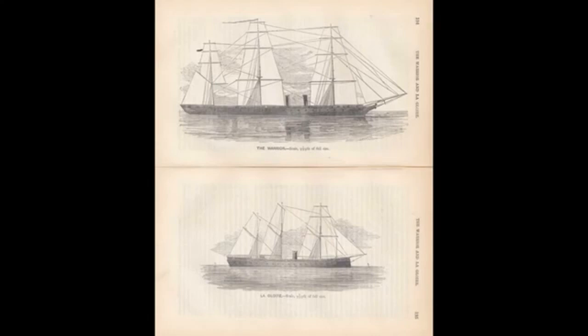Warrior's iron hull was a much better platform to mount the armour to, but its own plates were fitted together with tongue and groove joints. The theory being to distribute impacts that occurred close to the edges of a plate to adjacent plates, which was a good idea in principle, but turned out to be substantially less effective in practice, and the tongue and groove fitting made replacement and maintenance of the armour plates considerably more difficult than it otherwise needed to be.